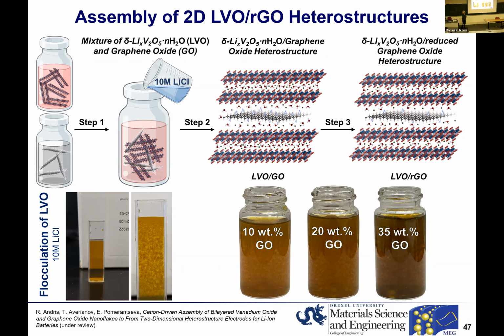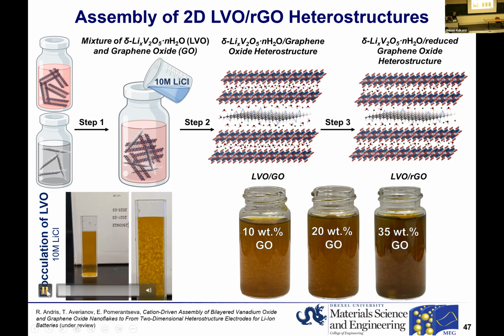Essentially what we do in this case, and this is shown just for the graphene oxide, because the color of the suspensions gets much darker and doesn't allow us to see much when we add bilayered vanadium oxide. So hopefully you can see these droplets, this is 10 molar lithium chloride that's being added, and you see the flocculation right away.